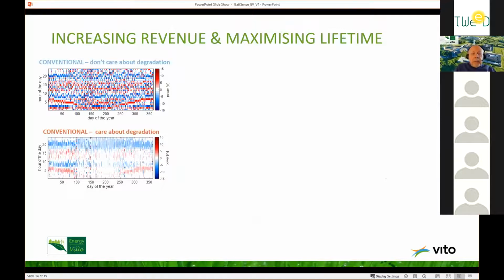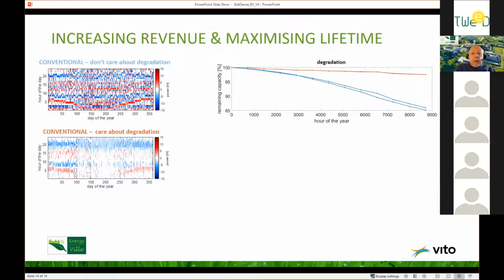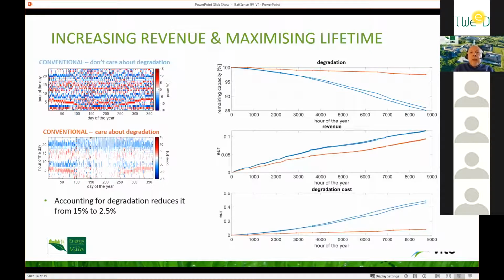When you care about the degradation and you limit the capacity of your battery, for instance, to 80% instead of delivering 100% of the capacity, you can already take into account a reduction in the degradation over the time of the battery. So this is already a way to reduce from 15% degradation to 2.5% degradation. But of course, the revenue generation is lower, but the degradation cost is also lower.